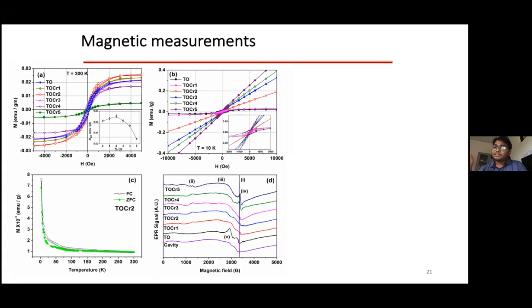So it so happens that for chromium in tin oxide, the solubility limit is reached by 2%. Beyond that, if you dope chromium, it will go into interstitial sites, and those interstitial site chromium will go back to its native antiferromagnetic exchange. So then you will start having two competing phenomena: ferromagnetism due to these vacancies and antiferromagnetic exchange because of these interstitially present other ions, chromium 3 plus.